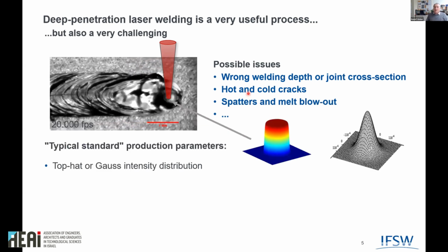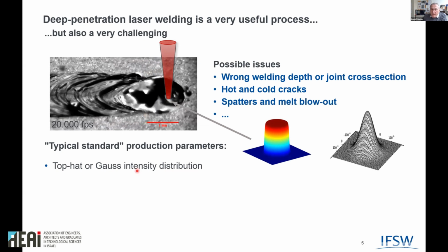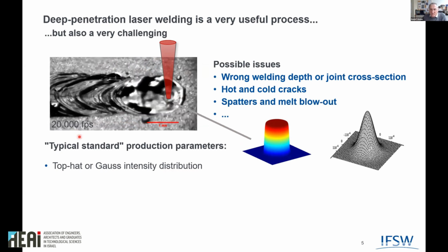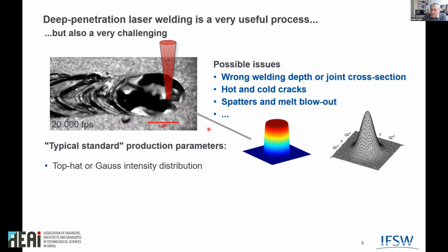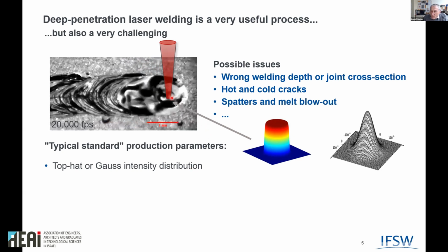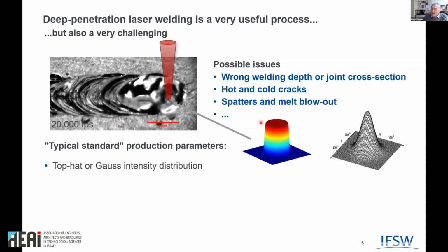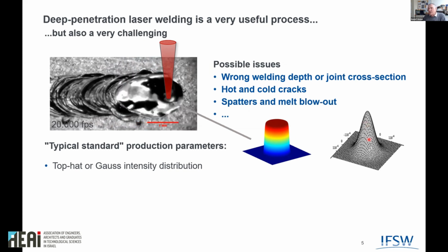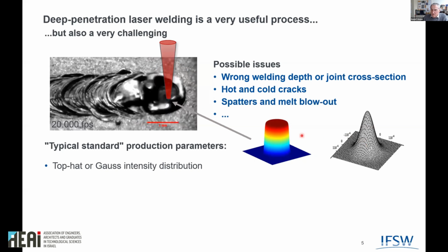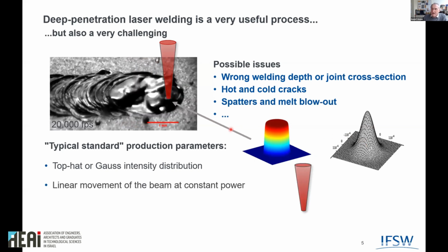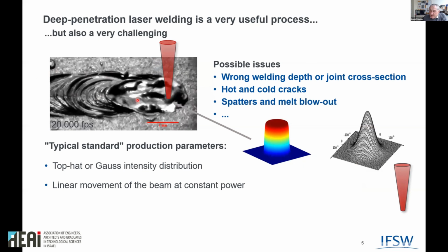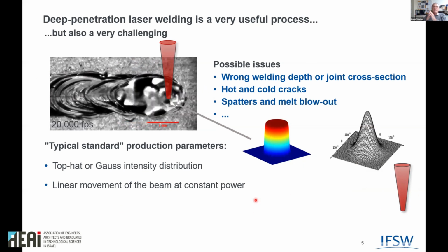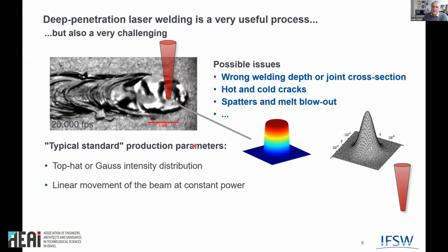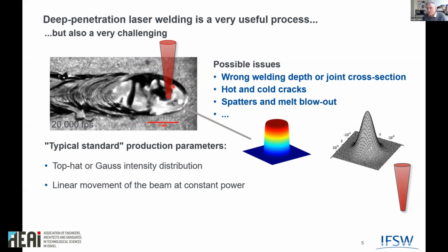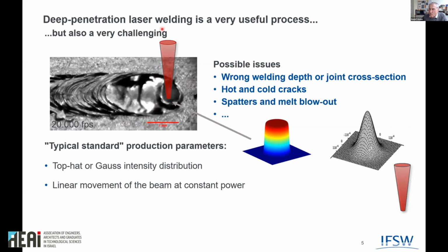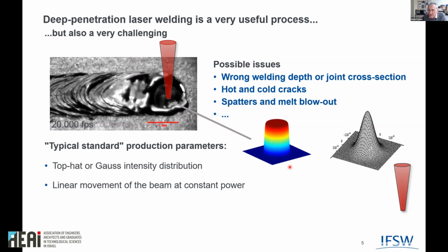and of course, what's going on with the laser beam. If you have a closer look again, today's typical standard parameter set, though it's not really standard, is that in the focus where the laser is focused onto, we have some top hat or sometimes some Gaussian intensity distribution. This is really common. That's usually done. And on the other hand, as you might see from this film already, the laser beam just moves linearly over the surface and doesn't make any additional movements or any additional power or intensity distribution changes during the weld.